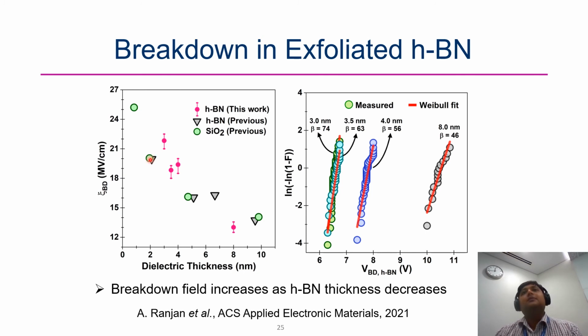And another question we were trying to understand is the statistics of breakdown, because it is very important to achieve robust statistics before the material can be integrated for any practical application. So what we have here is the breakdown voltage distributions for different thicknesses. In this case, we have 3 nanometer, 3.5, 4, and 8 nanometer. What we first observed is that the beta value, the slope, is very high, as good as SiO2, which tells us that there is very slight variation in these materials.